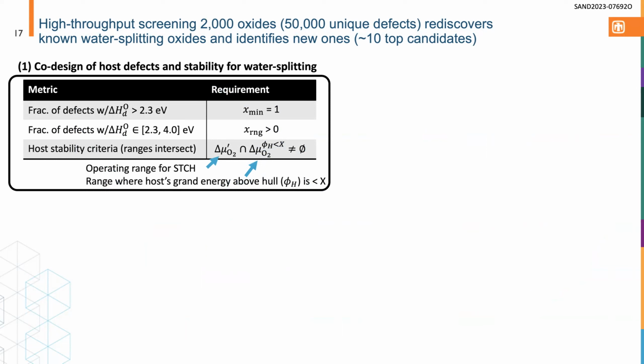Because of the data that was actually in our training data, we could only screen about 2,000 oxides out of the tens of thousands of oxides that exist in the Materials Project. That corresponds to 50,000 unique defects. One thing I didn't show here is that we confirmed that the model does not predict well on new crystal structures that contain cations that weren't in the training data. So that's why we're limited to only 2,000 oxides for now.